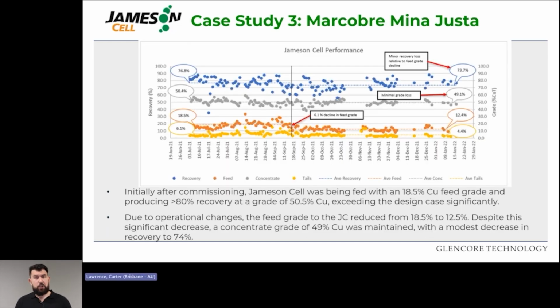Now, after initial commissioning, the Jameson cell was being fed with approximately 18.5% feed grade, and it was producing above 80% recovery at 50.5% copper. Exceeding the design case of 40% quite significantly.